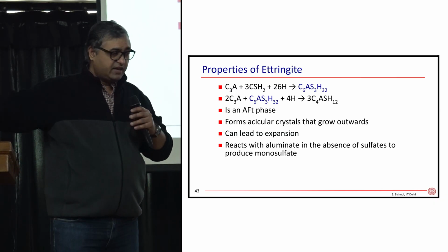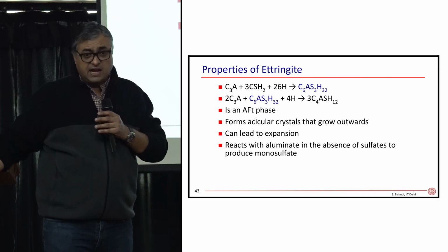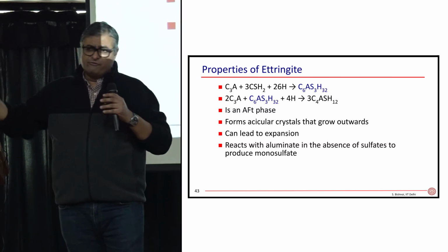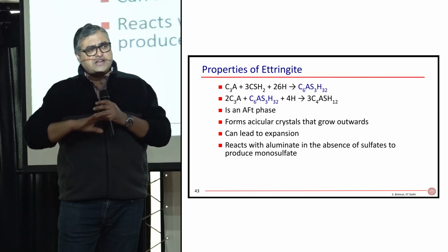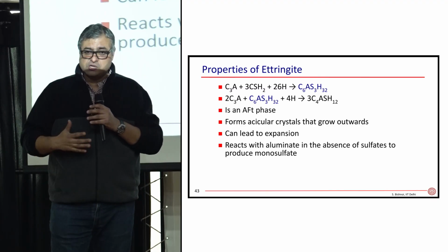The growth of ettringite can cause expansion because of that. It can push the particles away. It can lead to expansion. But in the beginning, when cement starts to hydrate, there's plenty of water, plenty of space around. So the ettringite can easily grow without having to push anything away.